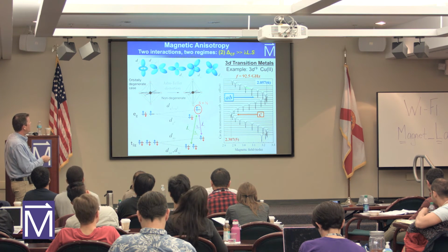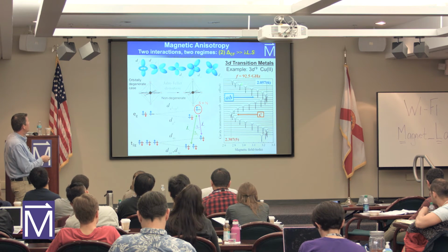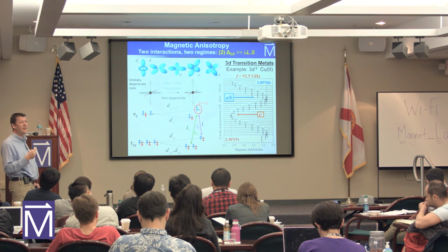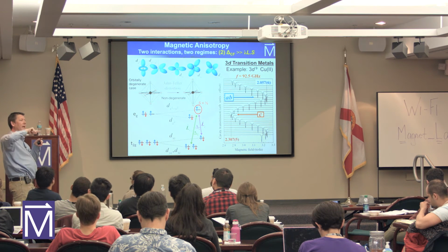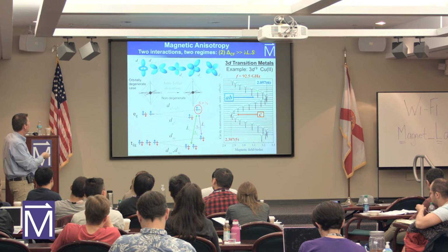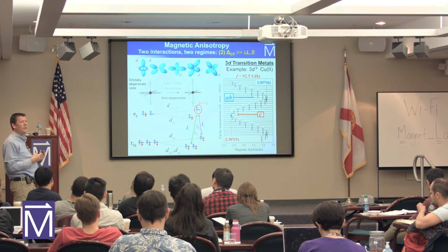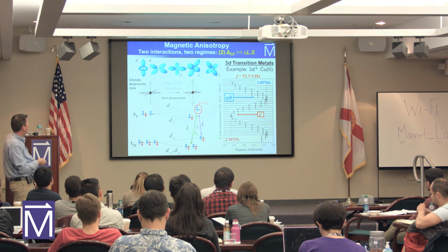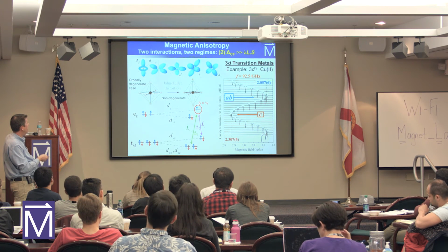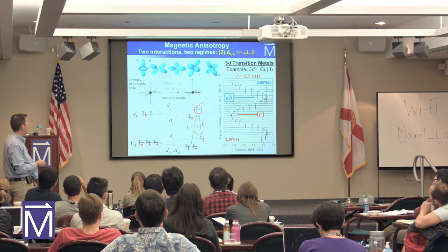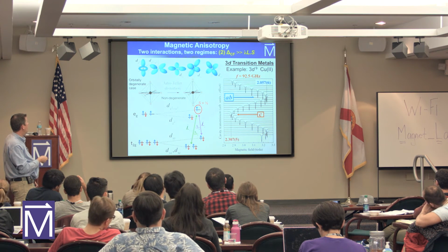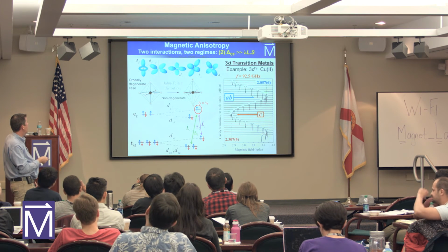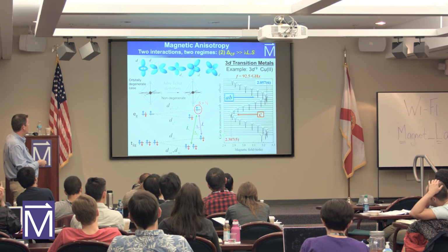Now we parameterize this all in terms of this g factor, which for a free electron is roughly 2. So when you have a g factor of 2, you have a Zeeman splitting of exactly 28 gigahertz per Tesla. But if it's slightly more than 2, then it would be a little bit more than 28 gigahertz per Tesla. And you can see for copper, in this Jahn-Teller distorted copper here, you have quite a large anisotropy in the g factor. It differs from one material to another, but very often for copper in a Jahn-Teller elongated situation, it varies from about 2.06 to about 2.3.